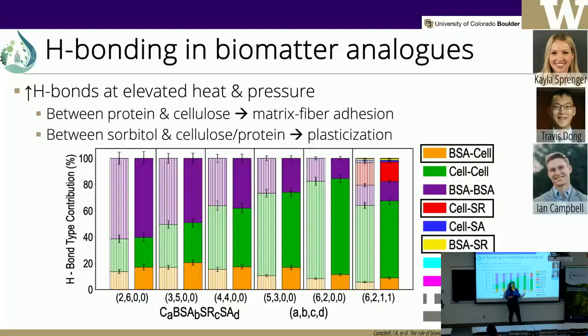So this, of course, if you know the structure of sorbitol, and you see all of the pending hydroxyl groups, and then you have cellulose, you would think, of course, they will click together and they will form bonds. Nevertheless, it's nice to actually see it, and to see that this is not disrupted, nor enhanced, by the hot pressing function. And then the other thing that we see is that the BSA with the sorbitol also interacts.